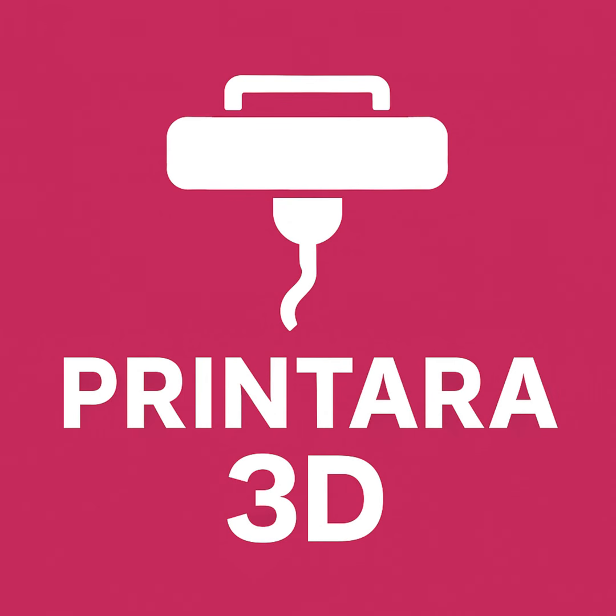That makes total sense. And in the absolute worst case scenario, that degraded, thermally altered material just builds up inside the melt zone, chars, and completely clogs the nozzle. You are fundamentally no longer printing with the material you thought you bought. Man, knowing that the moisture physically destroys the plastic structure at high heat changes the entire approach. It has to. We have to get the water out before it ever reaches the extruder gear.